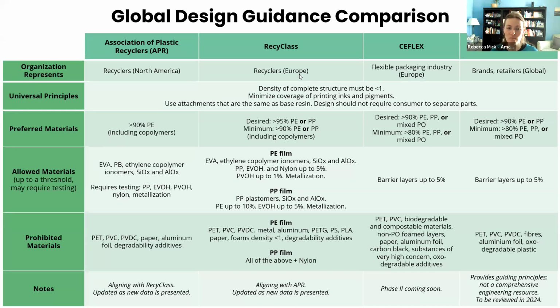So that's PE film. PP film, again, we can do PP copolymers, plastomers, things like that, as well as SiOx and AlOx. Again, PE is a contaminant in that stream, remember, so you can use that up to 10% and EVOH up to 5%. And then CFlex and the GDRs are much more general, just any of those barrier type materials up to 5%. And again, that's really because those are general guidelines versus the APR and Recyclass have really gone through, and the reason they have more prescriptive limits is because that's based on previous test results that they've seen, and they've actually shown compatibility up to those limits.